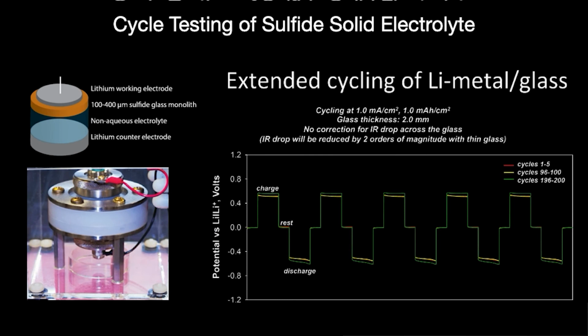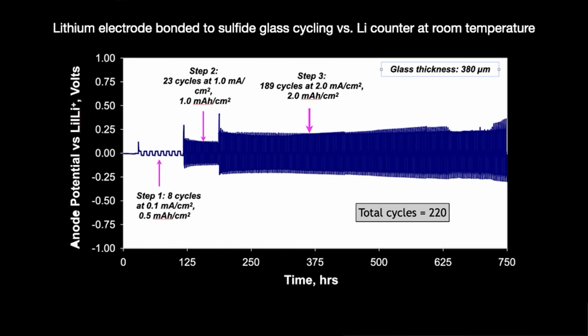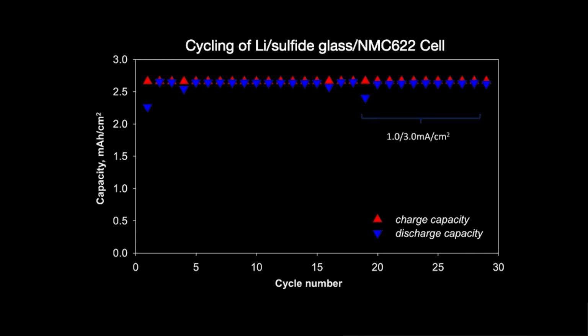We obviously cycle these. Most of these glasses have been cycle tested in small cells. We're getting ready to do larger cells. You can see here that after 200 cycles, the cycles basically fall right on top of one another. Here's some extended cycling of a 400 micron thick glass. You can see that it's very reversible. We don't see any evidence of dendrites. We also cycle these glasses against NMC 622. We see very good capacity retention there as well.